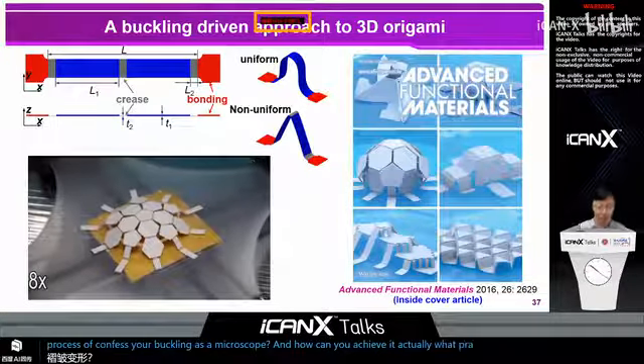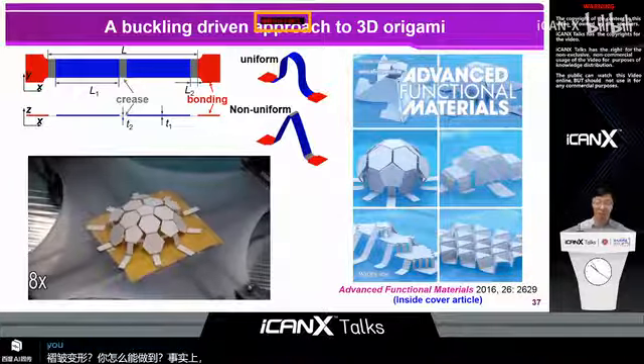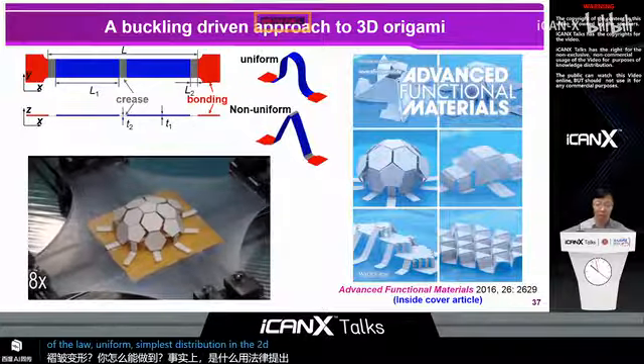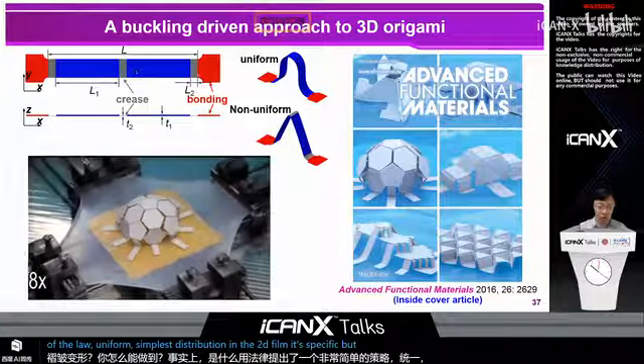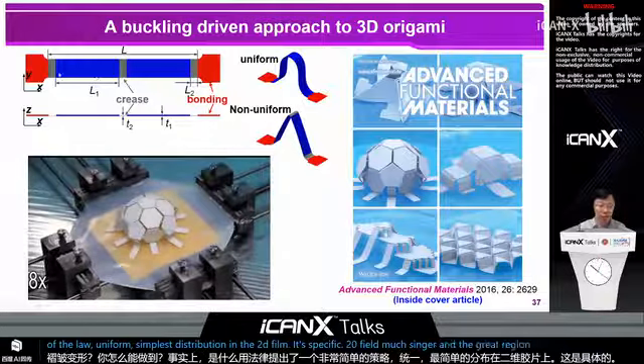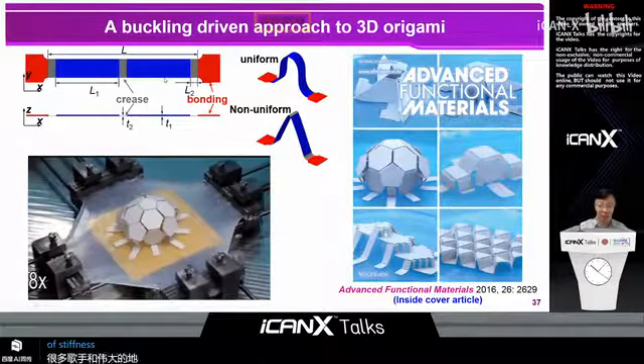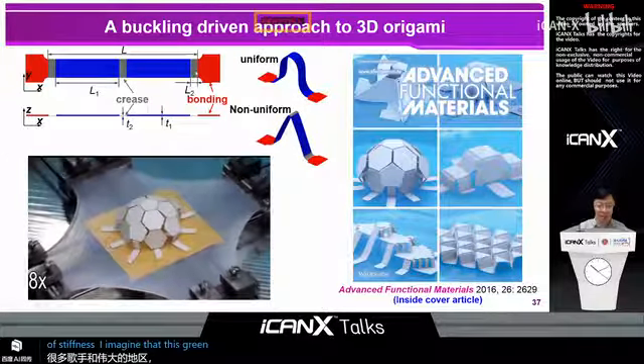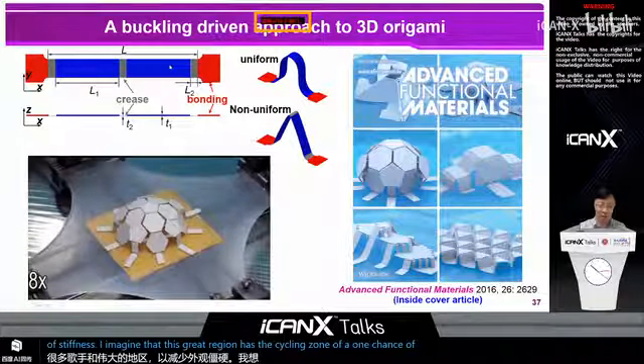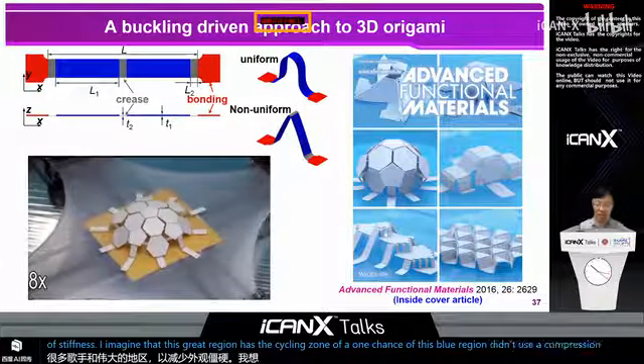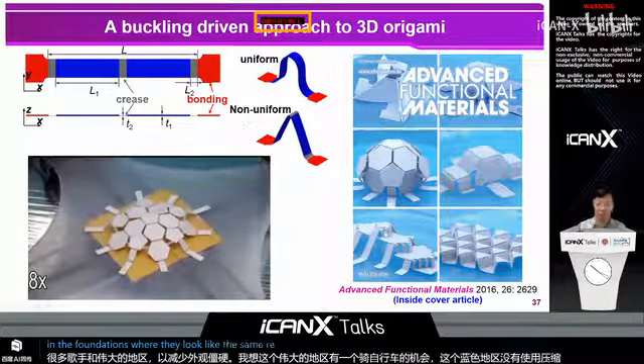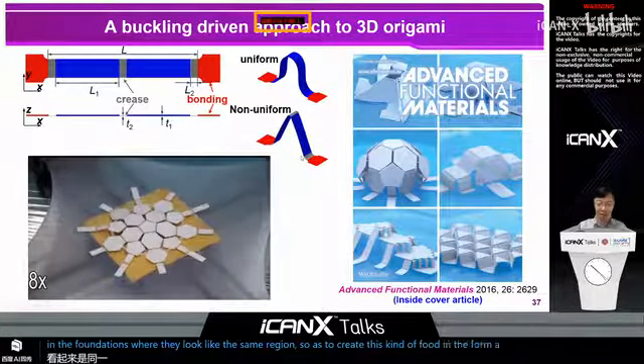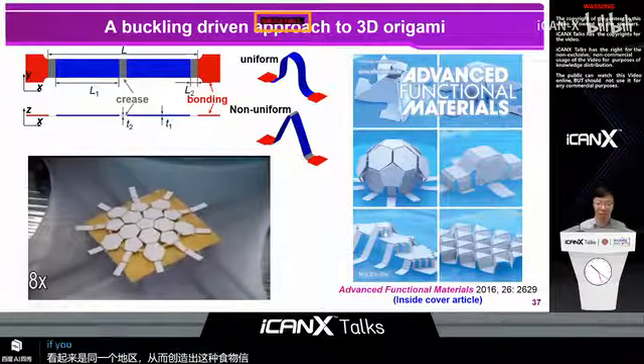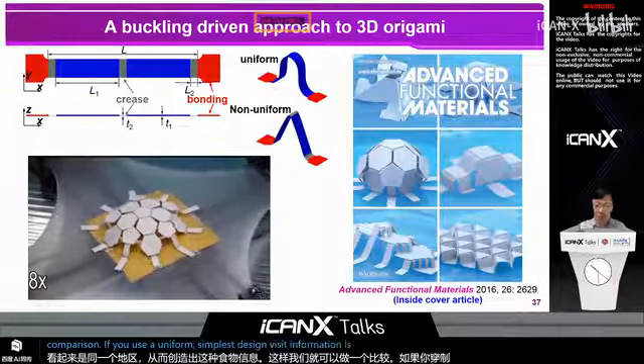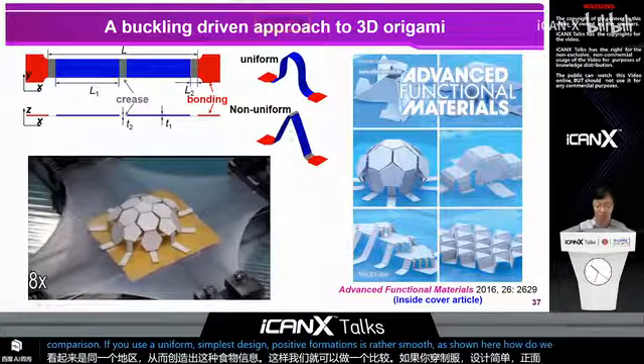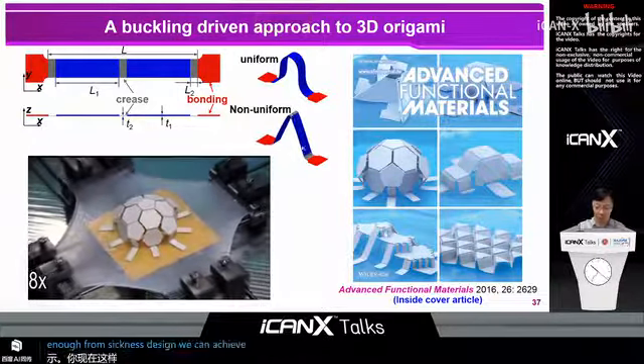Actually, we propose a very simple strategy by use of the non-uniform thickness distribution in the 2D film. Specifically, we make the 2D film much thinner at the gray region so as to reduce the local stiffness. You can imagine that this gray region has a thickness of 1/10 of this blue region. Then during the compression, the bending deformations will be localized at the thin region so as to create this kind of folding deformations. So here we can do a comparison. If you use the uniform thickness design, then the deformation is rather smooth as shown here. But when you do this non-uniform thickness design, we can achieve this kind of folding deformations.